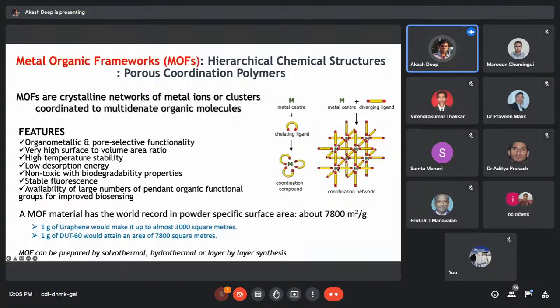And this selectivity is very important to capture specific molecules. For example, if I want to capture oxygen or hydrogen, I can take a diverging ligand which has a length similar to the oxygen or hydrogen molecule, and by choosing that length, I will end up fabricating a structure which can selectively capture only hydrogen or oxygen. So this is the pore selective functionality, which is very important in the field of metal organic framework applications, in catalysis, in gas capture, in environmental application, in sensing as well.